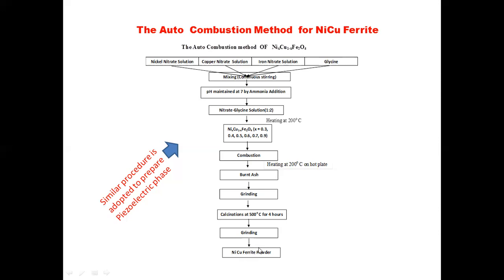But this is not possible when you are using the ceramic technique. To prepare the sample by the ceramic technique or the solid state reaction technique, at least 2 days are required. So that is the problem. And the powder obtained by the ceramic technique is also not in the nano range.